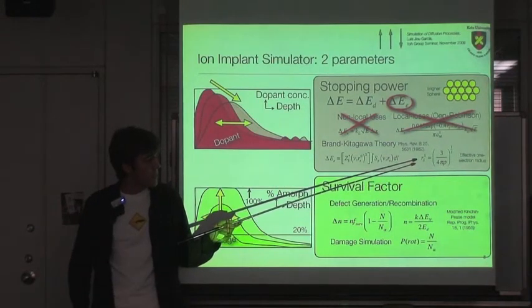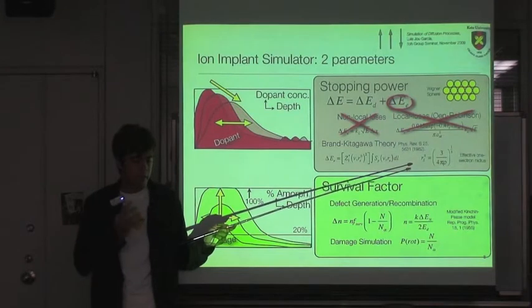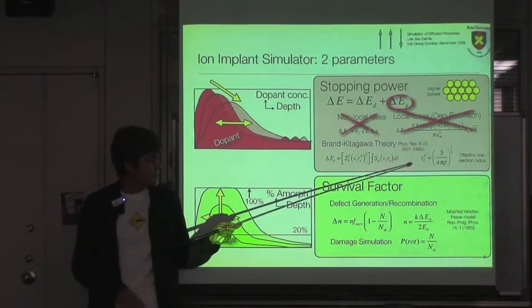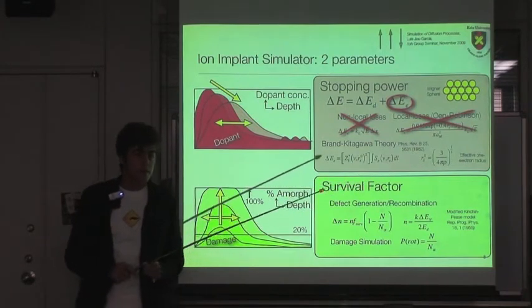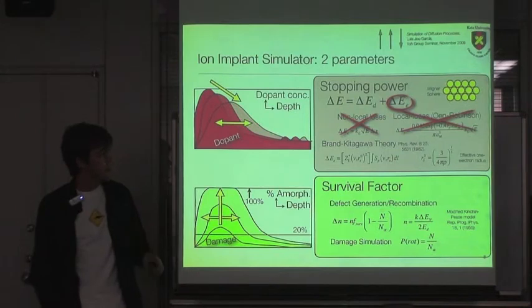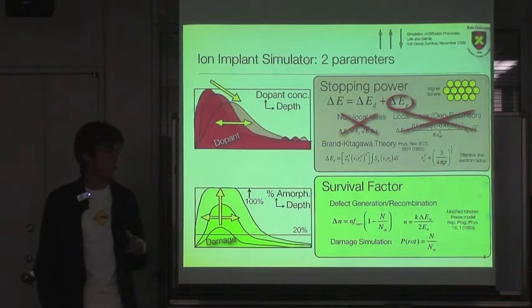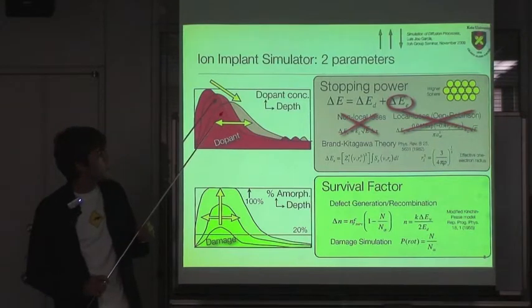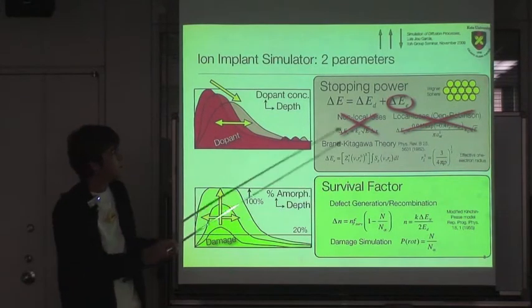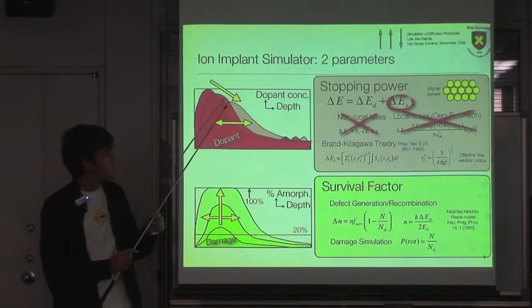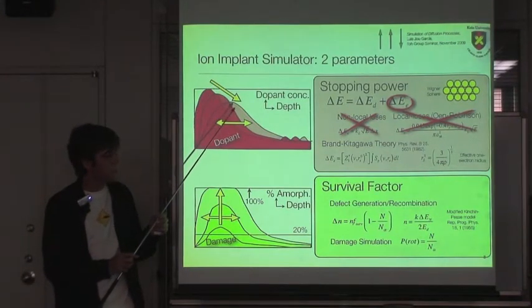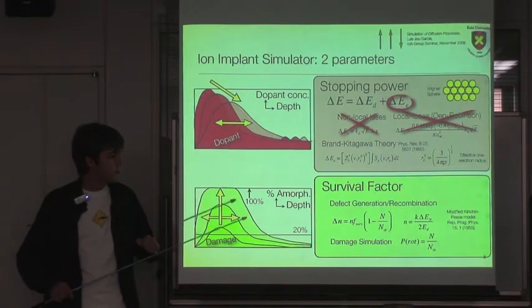That is something like how much background charge the projectile atom sees. This parameter changes for every combination of implanted dopant and bulk material, silicon or germanium, for example. And when we increase that parameter, we can see this effect on the dopant profile. It goes deeper and also it's wider.